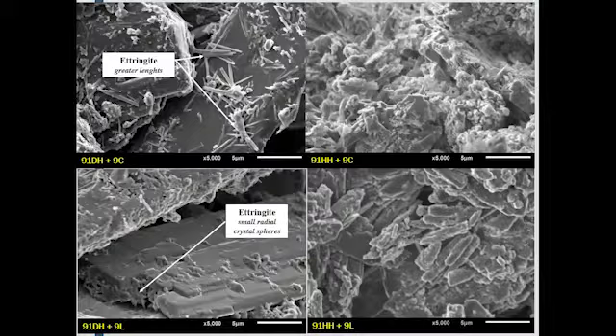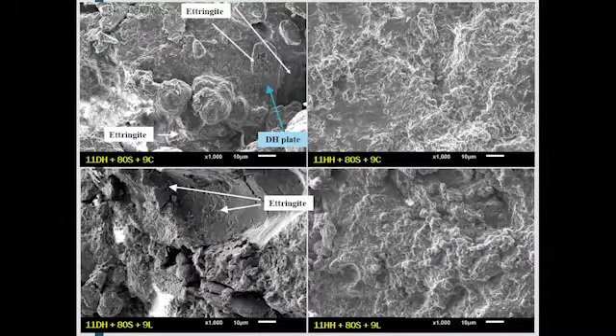For the mixtures with the DH, we observed that ettringite appears, but in different morphologies. In the cement mixture, we saw greater lengths, and in the mixture with lime, we saw small radial crystal spheres. And when you see these mixtures with the hemihydrate type, we didn't observe ettringite. In the mixtures with soil, with the dehydrate type, we see ettringite together with the phosphogypsum plate. With the hemihydrate, we cannot see it. And also here we can see agglomerations because of the chemical reactions. Here these agglomerations are bigger than here, where they are smaller. So here we can see a more homogeneous microstructure, and we believe that because of this, you have better mechanical behavior here than here.